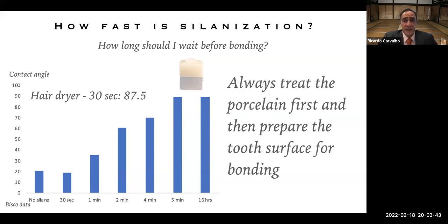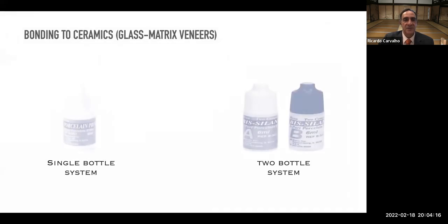What I usually recommend to clinicians is, if you don't have a hair dryer or any warm dryer, treat your porcelain first, apply your silane, and just leave it on the surface. Then you go to the tooth surface, isolation, etching, bonding to dentin, enamel, whatever you have to do, and within that time your silanization is progressing. By the time you are ready to apply your adhesive, your silanization is probably well progressed.